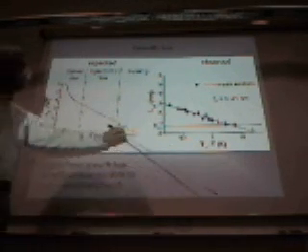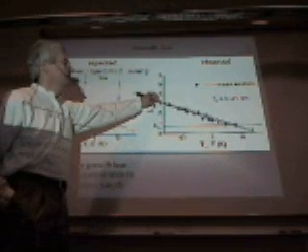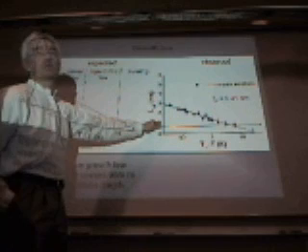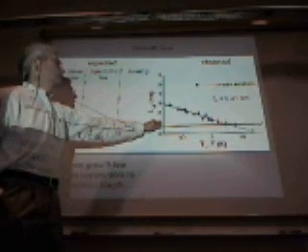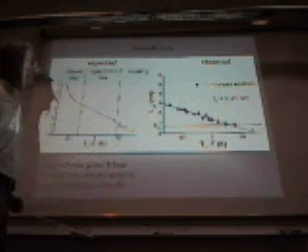Now let's see what we find in the experiment. When we take the smooth one, that's as observed, and plot this in this semi-log plot, you see this follows very nicely a straight line, down to, this is a double layer. This was the resolution we had in this first experiment. It's just a double layer of water molecules or ice. That's when we see the surface melting sets in.